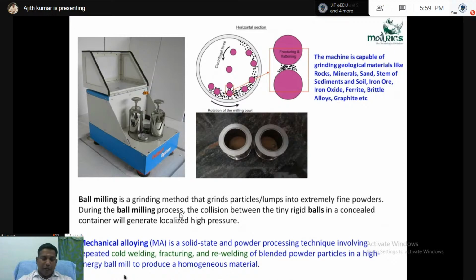By liquid metallurgy, it's easy because in liquid aluminum, if you put some cerium lump, it will immediately mix with aluminum. We can make aluminum cerium alloy or aluminum silicon alloy. But in the case of solid state, we are using ball milling. The mechanical alloying method is a solid state powder processing technique involving repeated cold welding, fracturing, and rewelding of blended powder particles in a high energy ball mill to produce a homogeneous material.